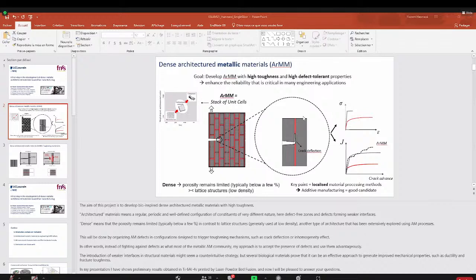Yeah, well, from a general point of view, you can, any process, even going out of additive manufacturing and metals, any manufacturing process in which you have, so the key point in architected materials is to have a fine control of the local properties. So in additive manufacturing, of course, you can play with the laser parameters, which allows you to change the microstructure locally. But any process in which you can control locally the properties of the material, if you can generate a strong contrast between the properties of the different materials, you can generate an architected material. And that's actually what has been done a lot.